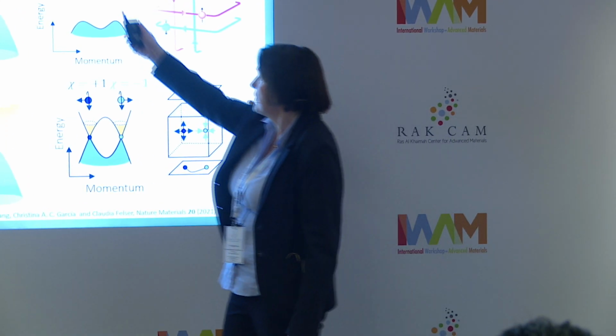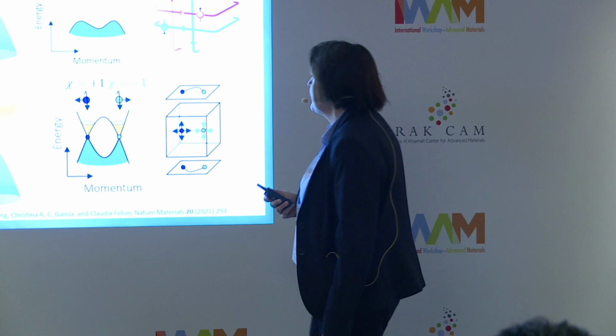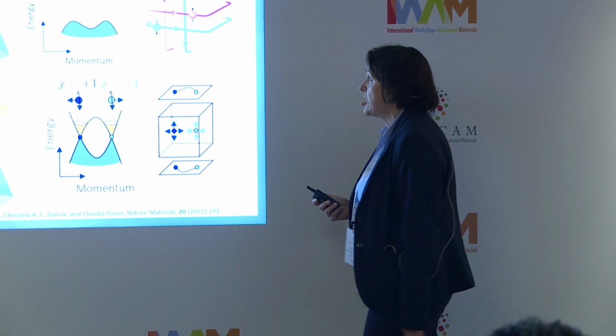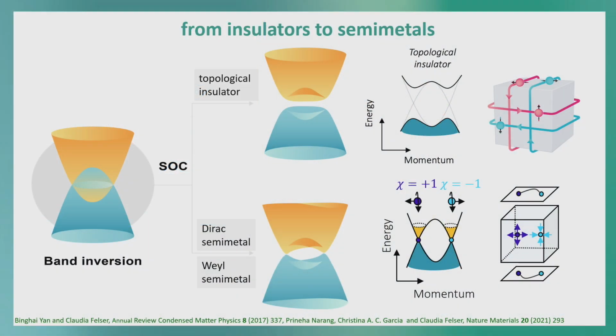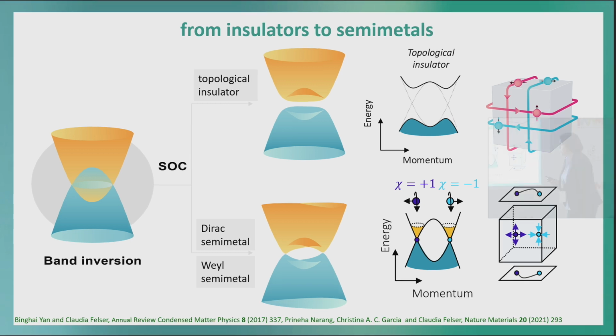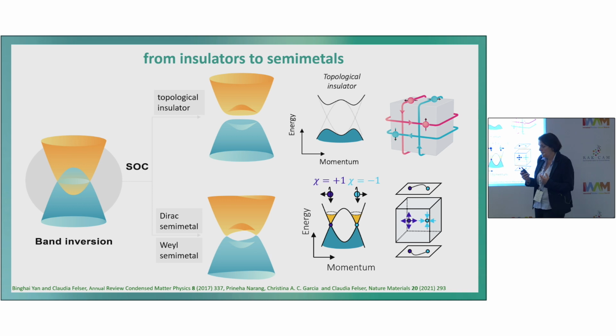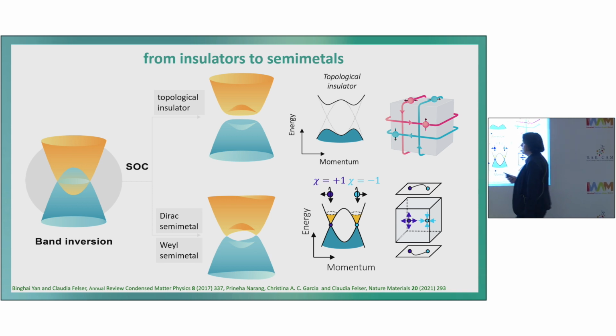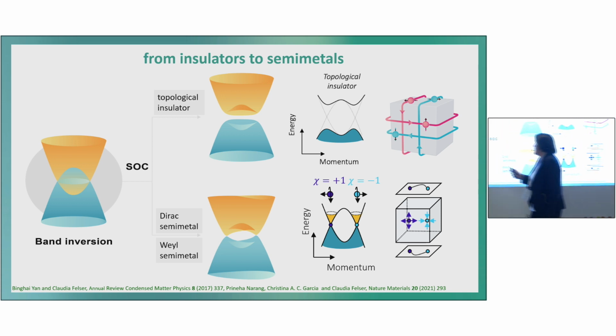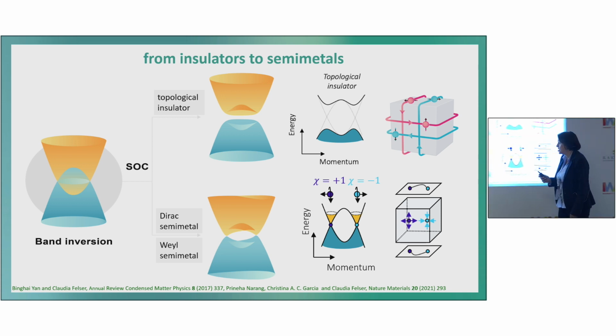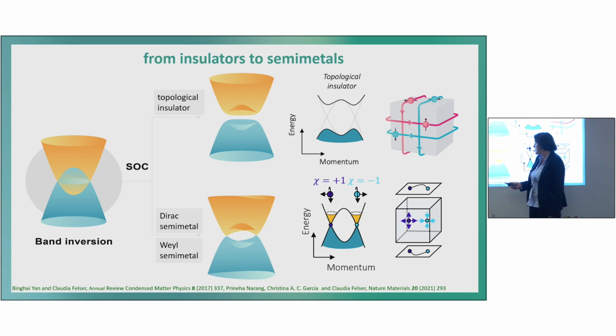They really connect valence band and conduction band. And this leads to these topologically protected surface states, which are also spin polarized, where the spin and the momentum are locked. But if we have other symmetries like rotation symmetries, it might be that certain points in this nodal line area are still allowed to be degenerate, and then we can get the so-called Dirac semimetals or Weyl semimetals.